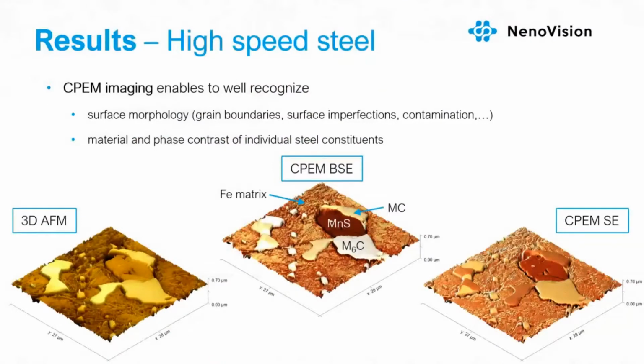The CPEM imaging of high-speed steel allowed us to distinguish different features on the surface. From the correlation, we can see which phase is higher, which one is lower. It is probably due to the fabrication process, but we can also see the diversity within one grain. Because on the BSE image, CPEM BSE, you can see that it is one grain on the left, but you have two colors of BSE. So it means you have within one grain two phases.